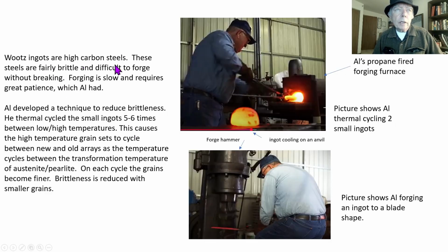Wootz ingots are high carbon steels. These steels are fairly brittle because of the high carbon and difficult to forge without breaking. Forging is slow. It requires great patience, which Al had, and I do not. Al developed a technique to reduce this brittleness, which I'll describe here.